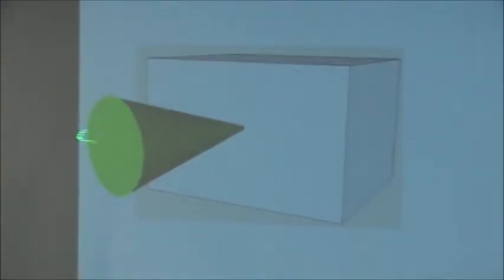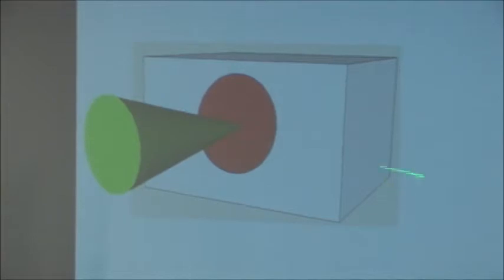Why? Here's the reason. Imagine you have a conductor. Imagine this is a piece of tungsten, bulk tungsten. In these experiments, like I said, we started focusing the laser. You focus a beam of light onto this piece of tungsten. Of course, you will generate some heat here. But what happens is that the heat spreads to a very wide area, right? Because conductors are good conductors of heat as well. So the result is that you don't get much temperature increase because this is acting as a heat sink.